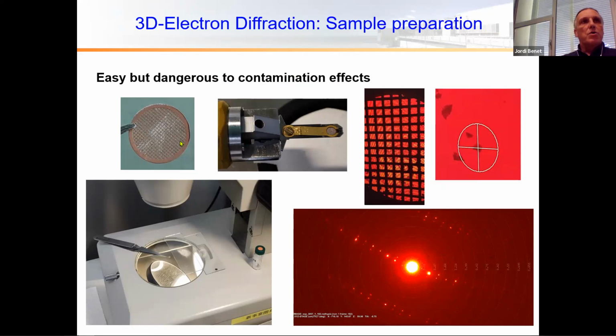Normally you use grids of different types and just have to deposit some of the sample on it. This grid, for example, is not well prepared. There's too much sample on it. In general, the amount of sample which you need, you cannot see with your eyes. And you just mount this sample with the grid inside the system. And then you start to look for crystals and measure them one by one, so that you have also on the electron diffraction system an image of the same grid where you can localize crystals and start to measure them and get diffraction patterns.